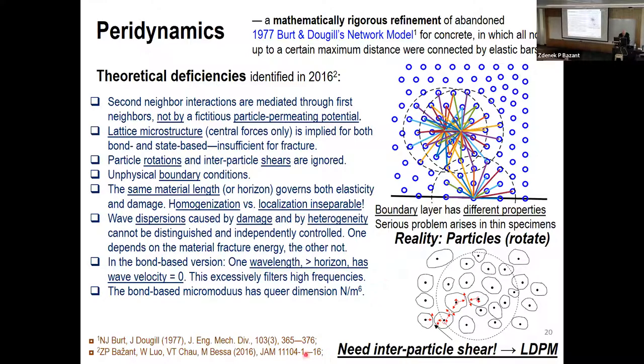This idea we criticized 6 years ago. I mentioned that in a theoretical paper, where I listed a number of problems. So I will not go through them because they're published. But let me at least mention, there is obviously a problem with the boundary. At the boundary, you have a lower density of connections. So you need to do something, increase the strength of the connections or the energy of the connections, but strength and fracture energy cannot both be matched, so there's no perfect solution.